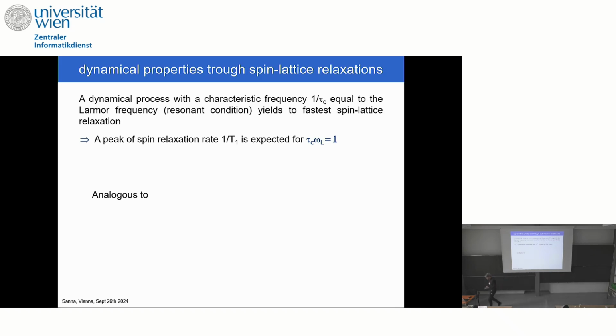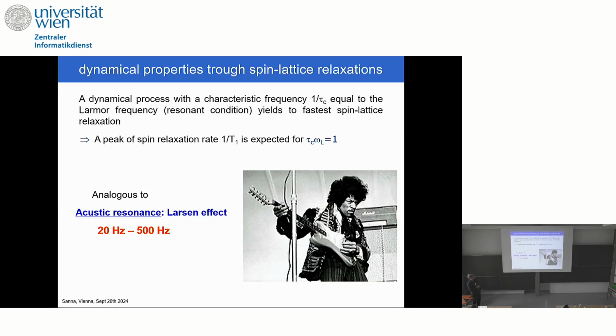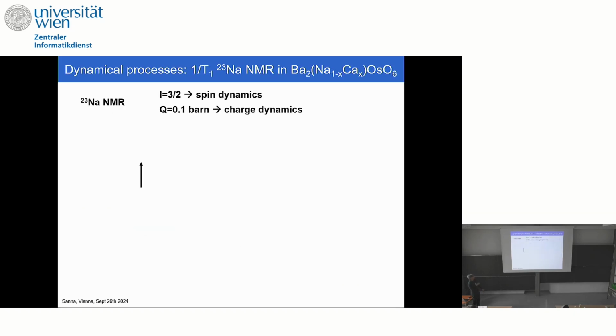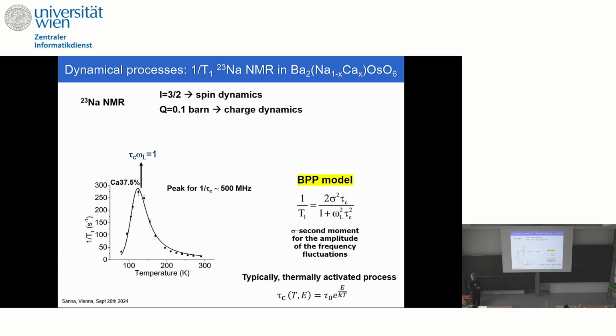This is very interesting because we have this effect that we can expect when we have some dynamical physical process with a characteristic frequency, 1 over the correlation time, equal to the Larmor frequency in an NMR. So we have this resonant condition. If this condition is satisfied, then you expect a large response of the system, which is measured by detecting the 1 over T1 relaxation time. And this is what we did. By measuring the system as a function of temperature, we have a peak. This peak means that there is some fluctuating phenomenon which has a frequency at around 100 Kelvin of about 500 megahertz. This is the physical meaning of that.